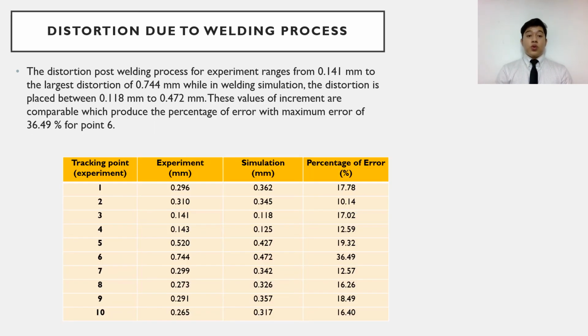The post-welding distortion for the experiment ranges from 0.141 mm to 0.744 mm, while in the welding simulation, the distortion is between 0.118 mm and 0.472 mm. These values of increment are compared in a table, where the maximum error produced is at point 6, which is 36.49%. This is logically presented, as point 6 is located at the end of the weld bead, which experiences the cooling process and produces the highest distortion.